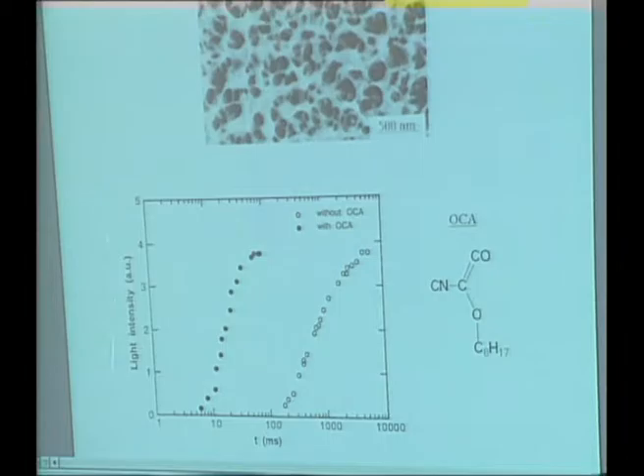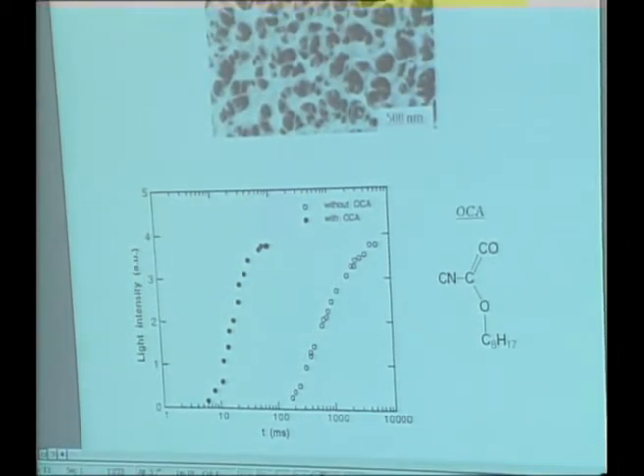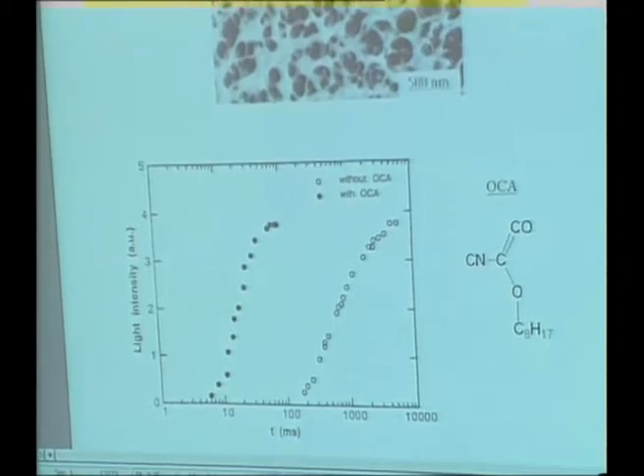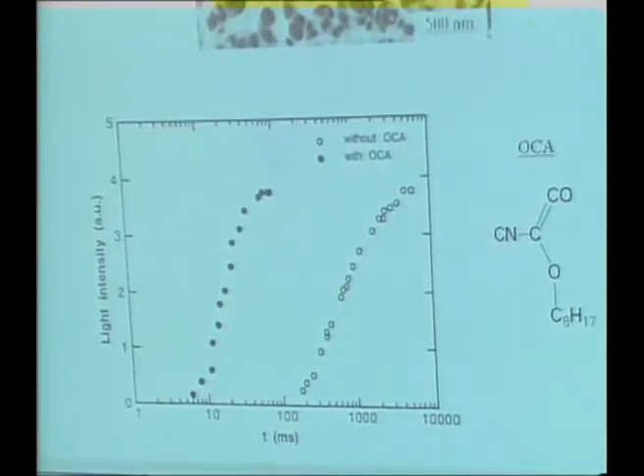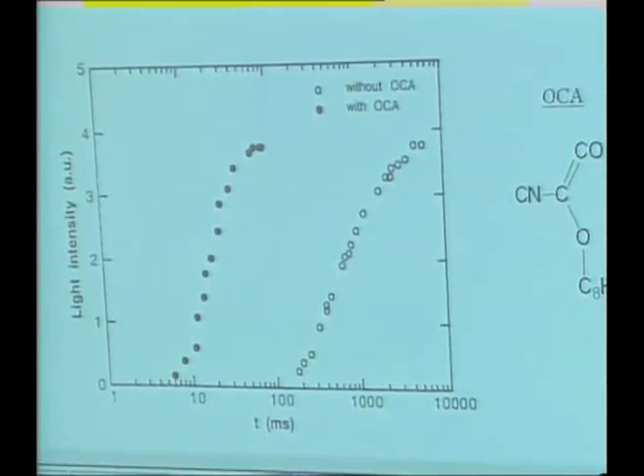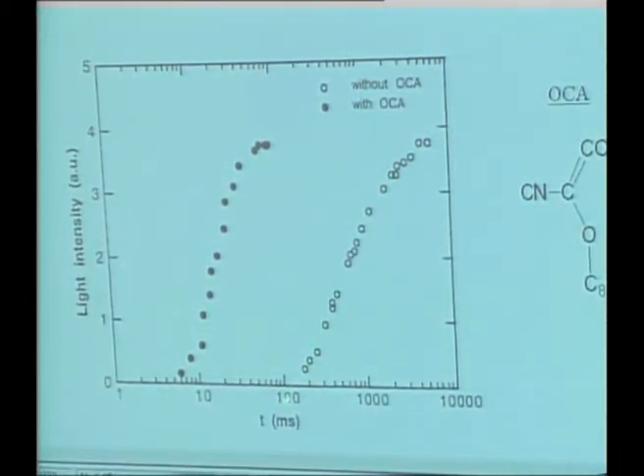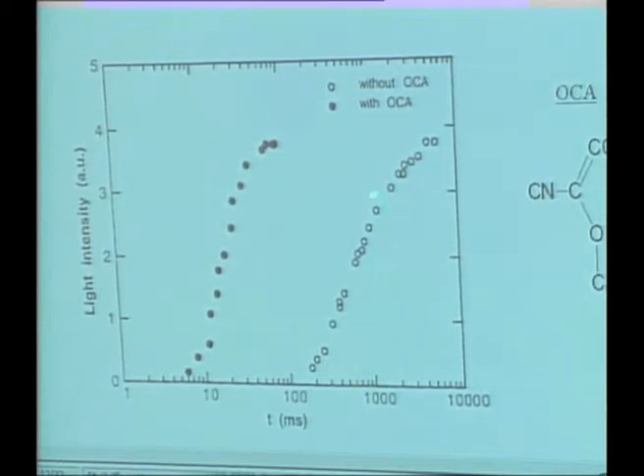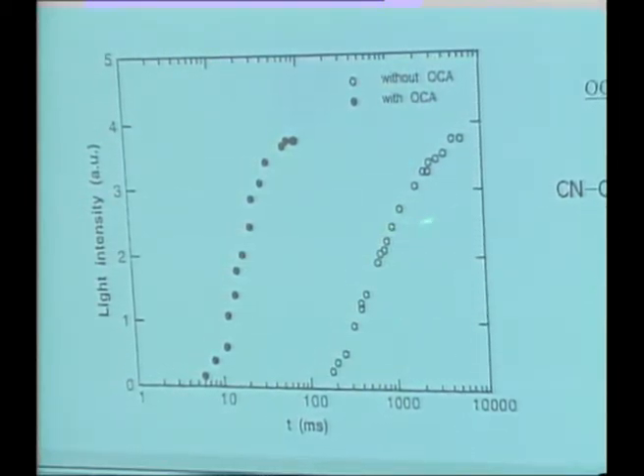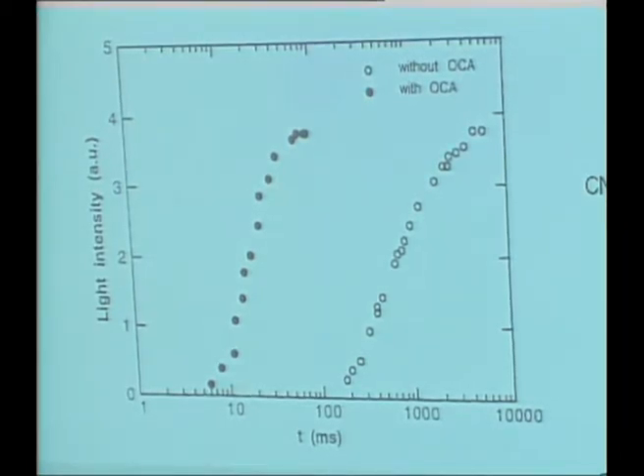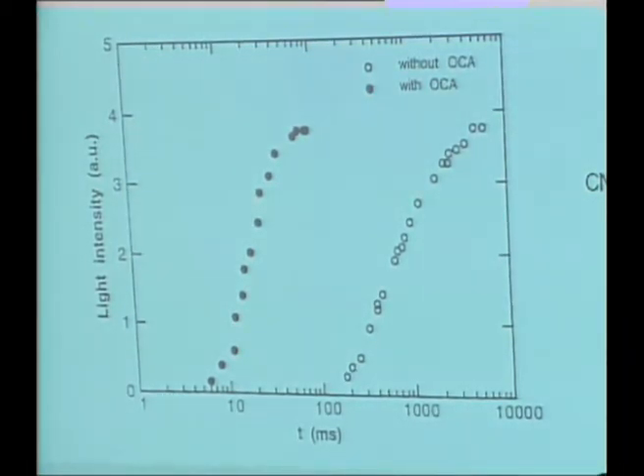And notice what happens, okay? So here's the light intensity, and we're pulsing on the device. And if you do not put this molecule in, so that you have a much bigger length scale in the structure, it takes a long time for it to turn on. This is 1 second here, the log scale, okay? But when you put the OCA in and improve the microstructure, then instead of 1 second, it's whatever, 10 milliseconds. So it works, okay? Now, I'm not claiming it's optimized, but you see the idea.